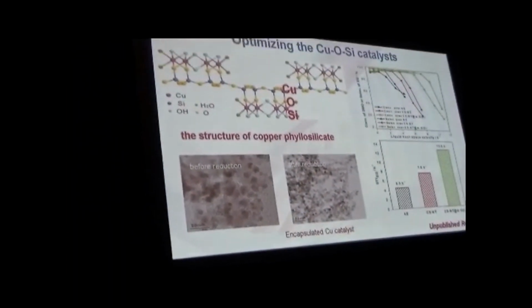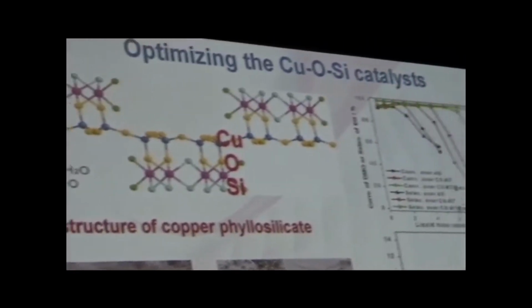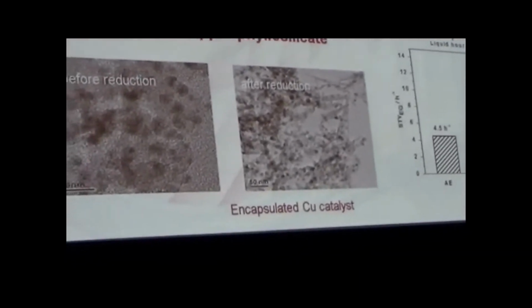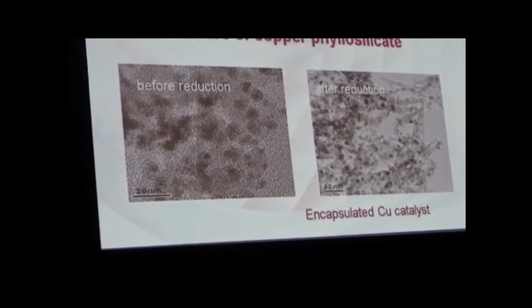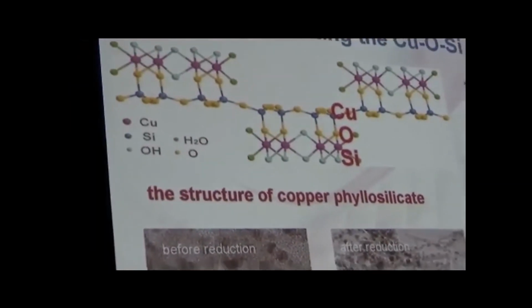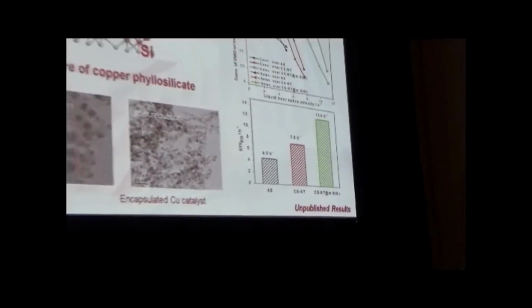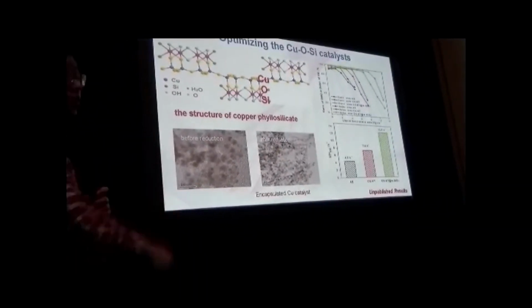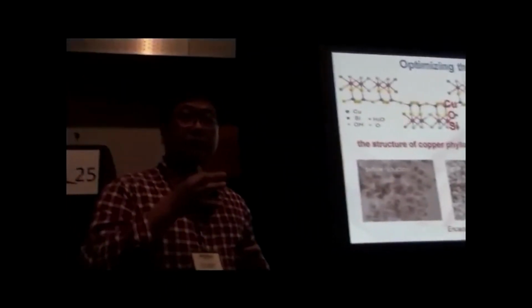Here, with this understanding, we can design a new catalyst. Here is the copper phyllosilicate. In copper phyllosilicate, we have copper-oxygen-silicon, already in this precursor. So when we use this as a precursor, we can make copper nanoparticles with very good copper dispersion. The activity of this is higher than the conventional one. And then moreover, we can coat the copper nanoparticle with the silicon. When we reduce the active site, but we increase the interface site, in this case, we can increase the activity again.